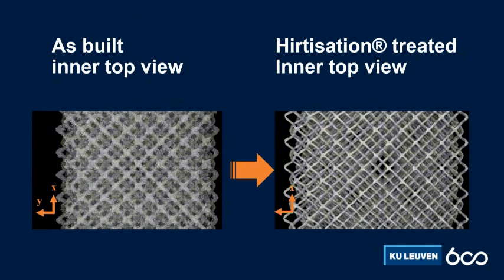Now, how is this achieved? What we see here is a cross-section of the top view of the lattice structure in the as-built state from micro-CT. If you observe closely, you will see a lot of semi-fused particles attached throughout the struts in the entire lattice structure. On the other hand, after the Hirtisation, those semi-fused particles have been successfully removed throughout the entire lattice structure, thus promoting a more uniform surface and a more uniform load distribution throughout the structure.